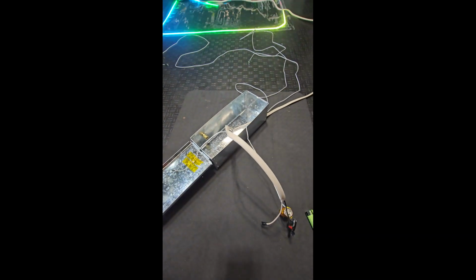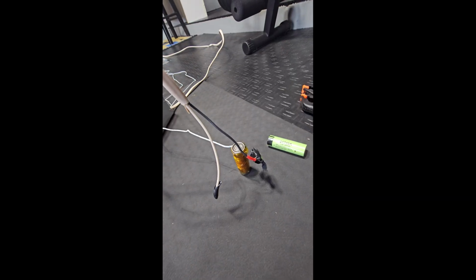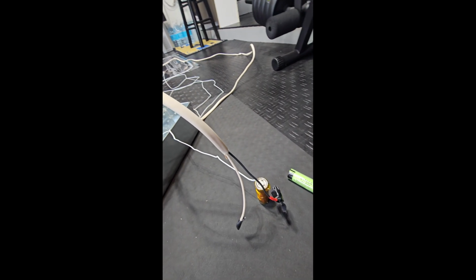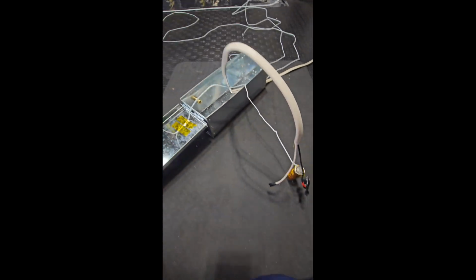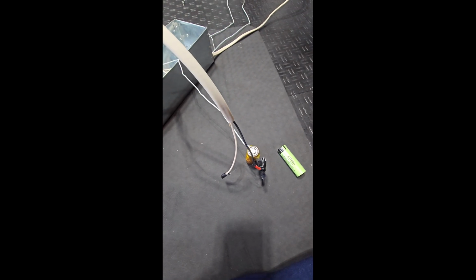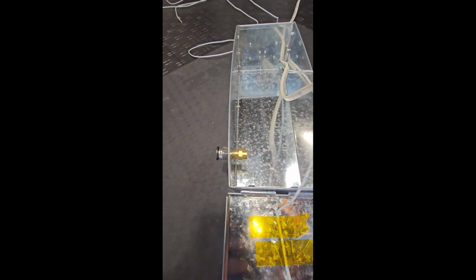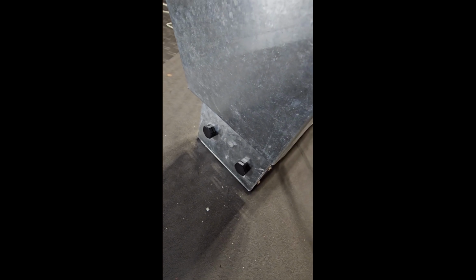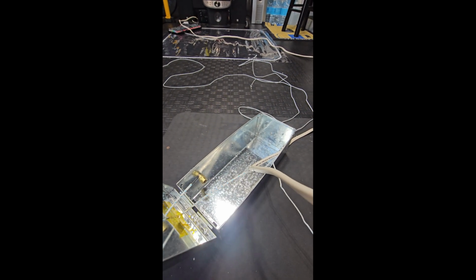All right. So we're building the test setup here for running this PPR test. We've got the nichrome wire already wrapped around the cell. We've got a thermocouple on the cell to measure the temperature as we're heating it up. There's a thermocouple in the box, and a pass through here to connect a tube to the pressure transducer. I installed two vents here. We're going to be putting thermocouples at the vents so we can measure the vent temperatures. So we'll have the internal temp with this thermocouple, we'll have the cell temperature until it goes, and then we'll have the vent temperatures.